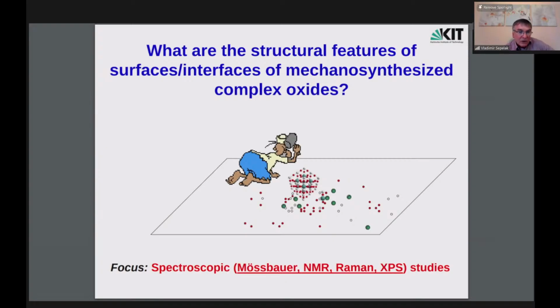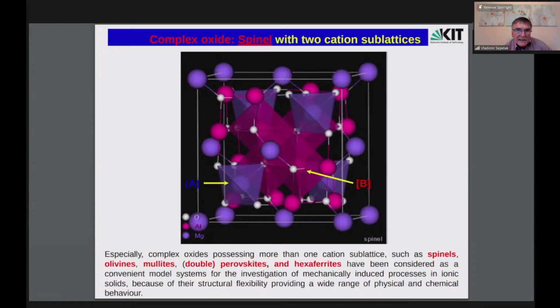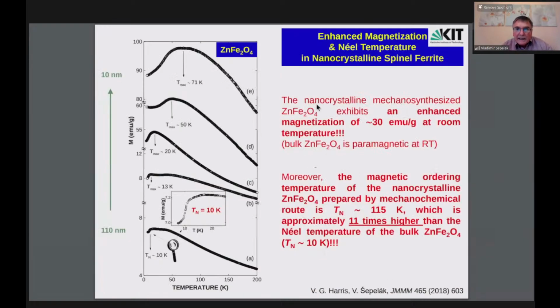These materials have been considered as a very convenient model system for investigation of mechanically induced processes in ionic solids because of their structural flexibility, providing a wide range of physical and chemical behavior. Let's start with zinc ferrite, which is a spinel and which is paramagnetic at room temperature. We showed in this publication that nanocrystalline mechanochemically synthesized zinc ferrite exhibits an enhanced magnetization of 30 emu per gram at room temperature, and the magnetic ordering temperature of the nanocrystalline material prepared by the mechanochemical route is about 11 times higher than the Néel temperature of the bulk zinc ferrite, which is 10 Kelvin. This bulk material is always the reference material, and we always prepare it using conventional ceramic high-temperature synthesis methods.